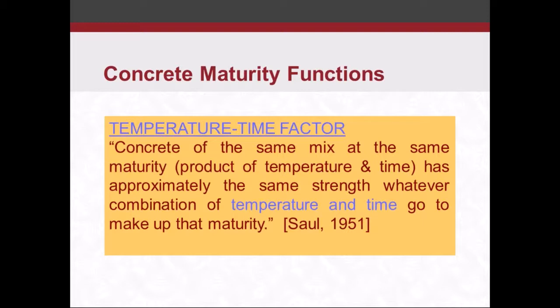So we've got 2 different concrete maturity functions that we can evaluate. One is a time temperature factor. This is based on the Nurse-Saul equation. Saul, back in 1951, made this statement: concrete of the same mix at the same maturity, and maturity is simply a product of the temperature and time, so temperature multiplied by the time, has approximately the same strength, whatever combination of temperature and time go to make up that maturity. Again, it's a fancy way of saying that the strength is a function of time and temperature.